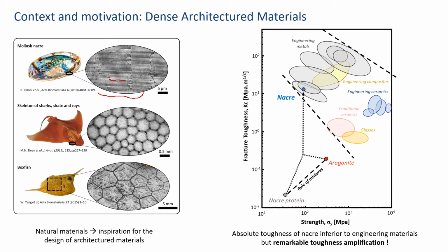And the thing is that if you look at the fracture toughness of these two constituents, it is relatively low. However, by combining these two constituents in this very beautiful architecture, natural evolution has found a solution to generate nacre, which is very high in toughness when compared to the base constituent. And this is due to different toughening mechanisms which are active in the material. So to put it simply, for example, the bricks are sliding on each other, increasing the size of the process zone, dissipating energy, and this is why you have such a remarkable toughness amplification.